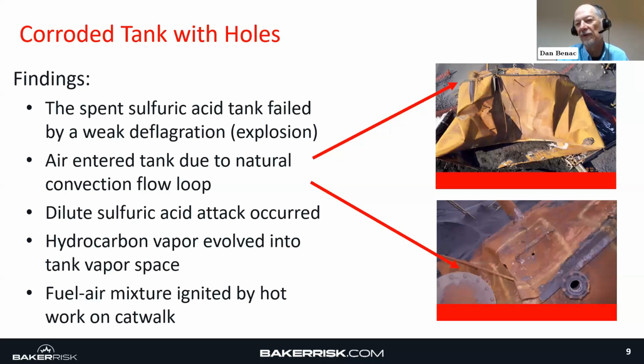As you can see here, this was a view from a lift where I was taking pictures of this particular tank. What we determined in our investigation, a very complex investigation that took many years before it finally all settled, at a very high level, is that air had entered into the tank. You had spent sulfuric acid, so hydrocarbon vapors were present. And then in this vapor space, there was a fuel-air mixture such that a spark from the hot work had thrown itself into the tank because there were holes on top of this tank. Not only were there holes on top of the tank, but in the lower picture you can actually see some of those holes. So it was just a spark basically that got in there, and it caused that failure to occur.